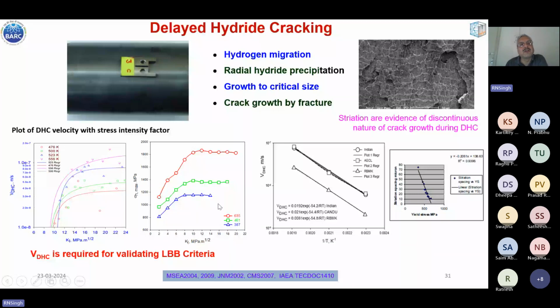The main driving force for hydrogen migration is hydrostatic stress. So if you plot the hydrostatic stress as a function of the stress intensity, and this is for material of different yield strength, you see that beyond a certain stress intensity, the hydrostatic stress becomes constant. With further increase in stress intensity, only the plastic zone size increases, and hydrostatic stress is not getting affected, which is the driving force for hydrogen migration. That's why, depending on the yield strength or temperature of the material, this plateau region is observed, where DHC velocity is independent of the stress intensity factor.